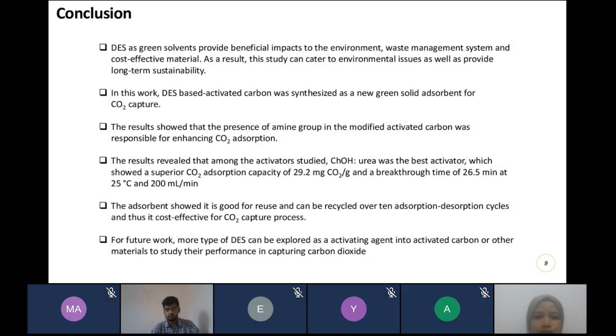In this work, DES-based activated carbon was synthesized as a new green solid adsorbent for carbon dioxide capture. The result shows that the presence of amine group in the modified activated carbon was responsible for enhancing carbon dioxide adsorption. Among the activators studied, choline hydroxide urea was the best activator, which showed a superior carbon dioxide adsorption capacity of 29.2 milligram carbon dioxide per gram. The adsorbent showed it is good for reuse and can be recycled over 10 adsorption-desorption cycles, and thus is cost-effective for the carbon dioxide capture process.